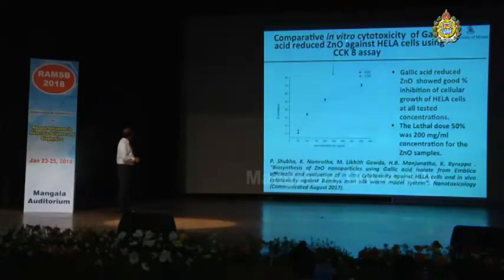And this is the comparative in vitro cytotoxicity of gallic acid reduced zinc oxide against HeLa cells using CCK8 assay. These are the standard kits available, and the biologists know pretty well about these HeLa cells and others. We have carried out this with gallic acid reduced zinc oxide. This shows very good inhibition of cellular growth of HeLa cells at all tested concentrations, and in fact the lethal dose 50% was about 200 milligram per milliliter concentration of these samples.